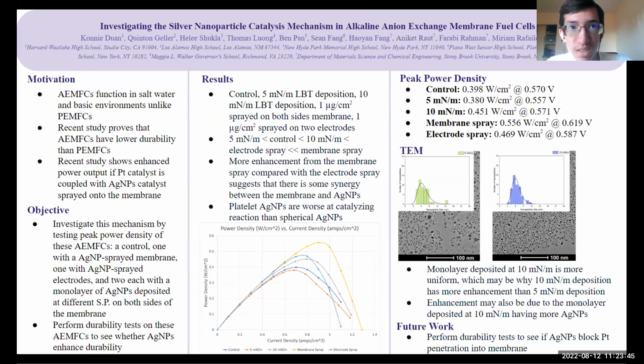The 10 millinewtons per meter deposition and the 2 sprays contained the same number of nanoparticles, but the membrane spray had a significantly higher power density, indicating a mechanism that does not benefit from the change in nanoparticle shape due to LBT deposition, but does involve catalysis of a nanoparticle membrane interface.